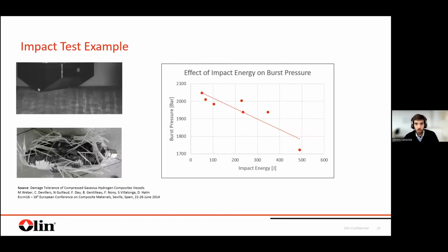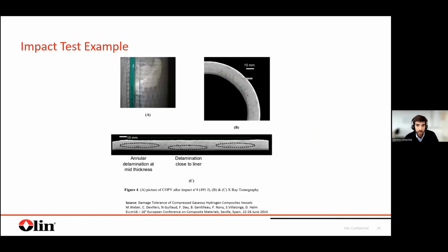Let's now go to the next one, where you will see the second example we want to show, which is the impact test. When generating a specified impact in specified conditions on an impact test that is needed to gain the type approval, you clearly see a correlation between the impact energy and the burst pressure of the tank. And a good question could be, why is that happening? Now, if you look at the pictures in the next slide, you will see that a reason for this correlation is the delaminations and microcracking that are generated during an impact. And delamination and microcracking are deeply dependent on the type of matrix that you are choosing.